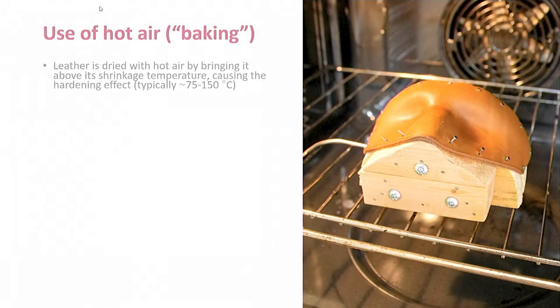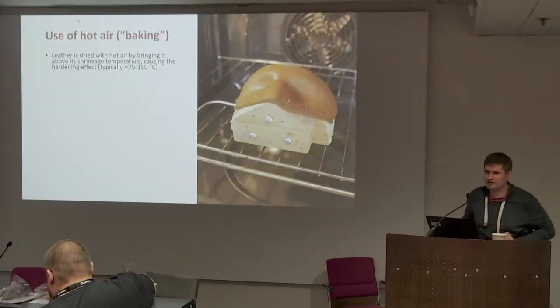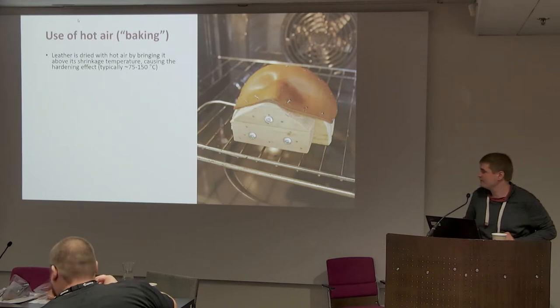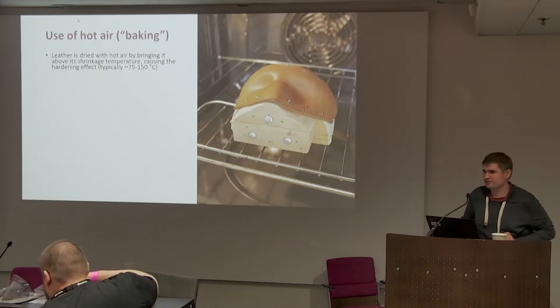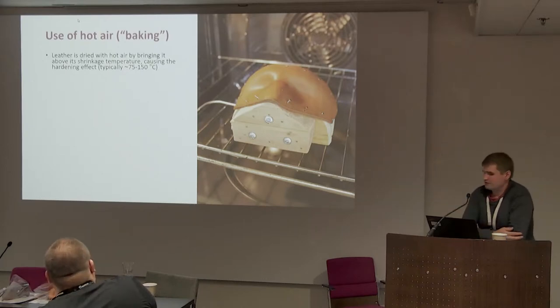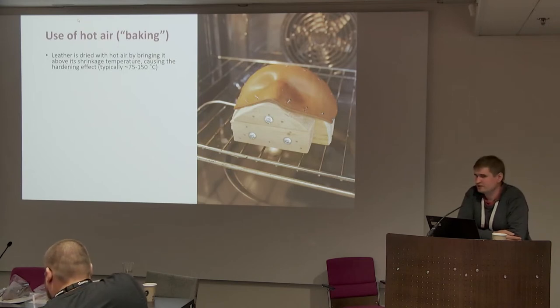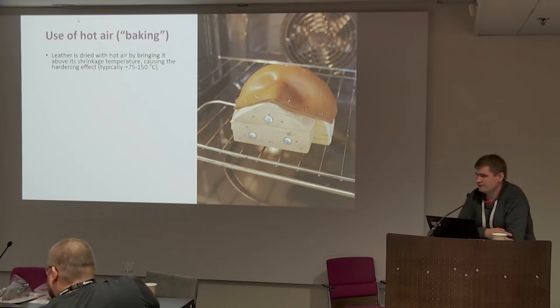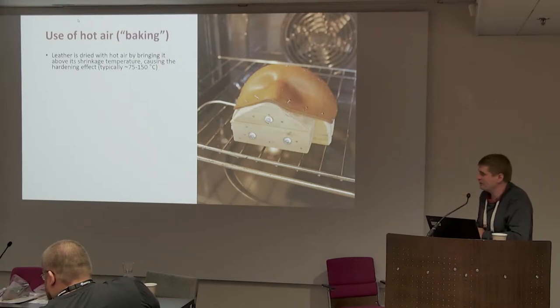Okay, next thing we have is the use of hot air, so baking. Leather is dried by hot air. This is typically done in temperatures like 75-150. You can get some stiffness out of the leather by doing something like this, but the results don't feel very convincing. We have a good deal of evidence that something like this has been employed historically. We have evidence of leather with elongated holes on the edges of the pieces that are consistent with something like this. So we have a wooden former and the leather constrained from its edges, and when it has shrunk while constrained there, you get the elongated holes.